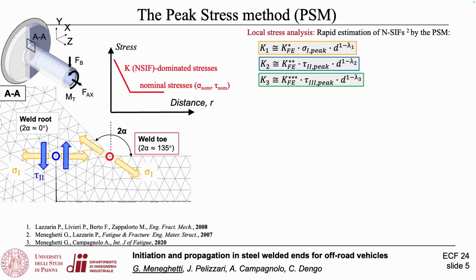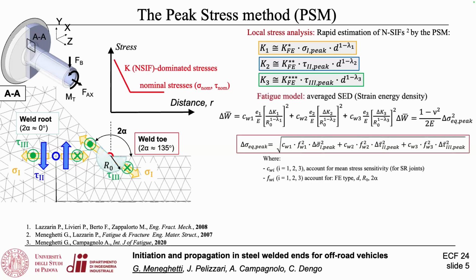The same can be done for mode 2 stresses, in-plane shear, and mode 3, out-of-plane shear. So in the end, if we take the linear elastic peak stresses at the weld toe and weld root, we can estimate all three notch stress intensity factors, and this is necessary for treating multiaxiality.